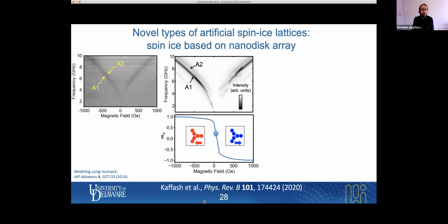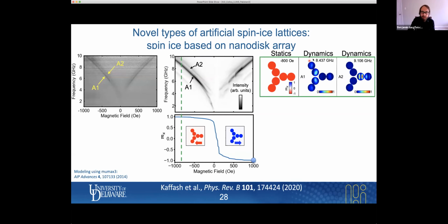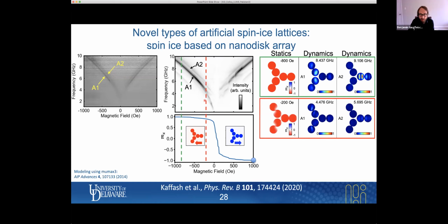All right, so the beauty now about micromagnetic modeling is that we can do these simulations spatially resolved. So I'm showing here the statics. This is the static magnetization configuration at -800 Oersted, this green dashed line. And I'm showing here 2 modes, the low frequency mode, A1, and the high frequency mode, A2. And what we observe here is that for the low frequency mode, the dynamics are located in the oblique elements, whereas the high frequency mode is located in the horizontal elements. Let's see how this behaves if we increase the field. So this is at -200 Oersted.